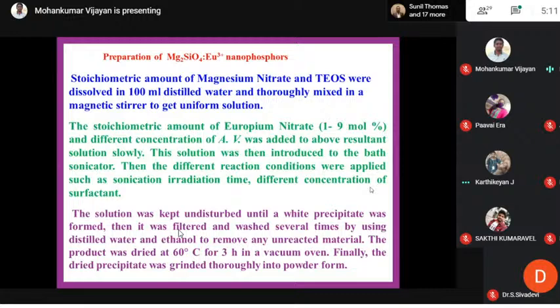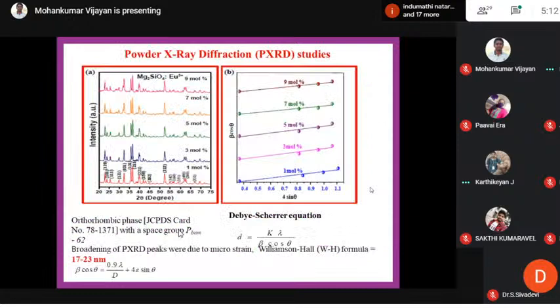So the product was dried at 60 degrees centigrade for 3 hours in a vacuum oven. Finally, the dried material is used for the calcination. So these are the two XRD diagrams for our sample. From this XRD diagram, we can say that our sample is crystalline and it is in orthorhombic phase.